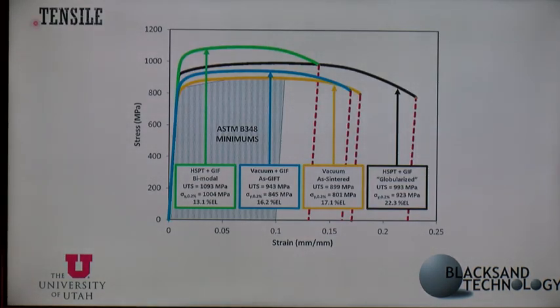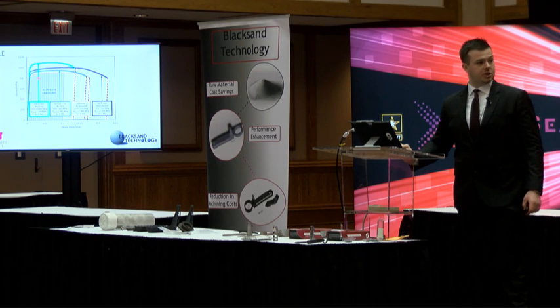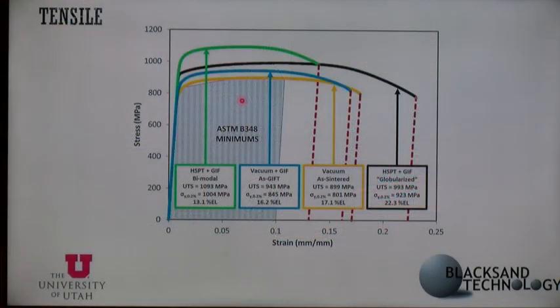So here we have a tensile test. There are basically two properties that we care about as metallurgists, or anyone really, and that's tensile and fatigue. Tensile is how much pressure the material can undergo before failing, and fatigue is how many cycles that material can undergo before failing, right? So here on the left, you can see in that shaded region, we have the minimums that ASTM requires. They require all titanium 6-4 to undergo this same test. And as you can see in the yellow and blue, that's what vacuum sintering basically shows: slightly above minimums, but not really that much better.